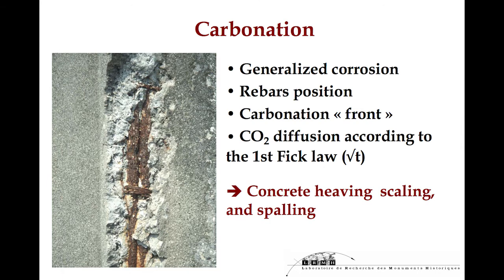So the carbonation leads to generalized corrosion. It depends on the rebar's position in relation to the carbonation front. And the CO2 diffusion follows Fick's first law, according to the time. So in terms of decay, we observe concrete heaving, scaling, and spalling.